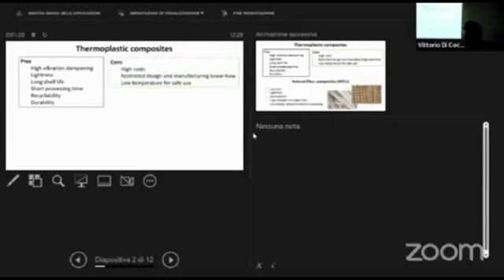But their wide diffusion has always been limited and slowed by the high cost of tools and materials, but also by the strict know-how about design and manufacturing, but also by the low temperature for safe use with respect to thermosetting composite materials, because in this case we have a glass transition temperature that usually is lower than 100 degrees. In case of epoxy resins or other thermosetting polymer composites, you may also have a glass transition that goes through 150 degrees or higher.